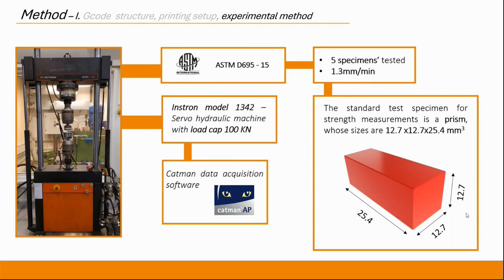To better describe the mechanical properties, 5 specimens are tested, aligning the principal axis with the load axis, and the speed of testing is set to 1.3 mm per minute. The compressive machine has a load cell of 100 kN, and the data acquisition is performed using Catman software.